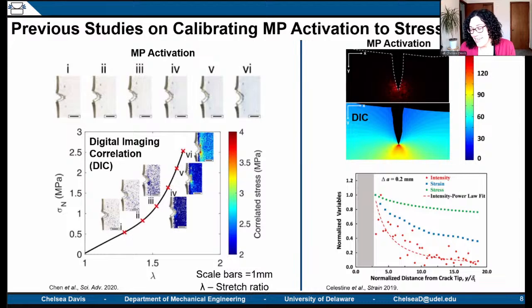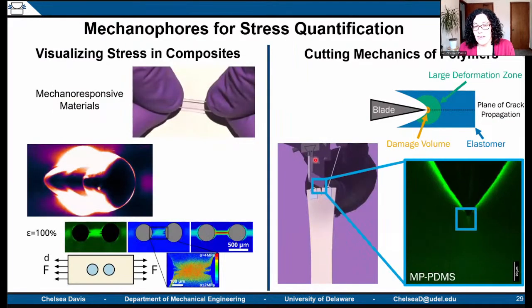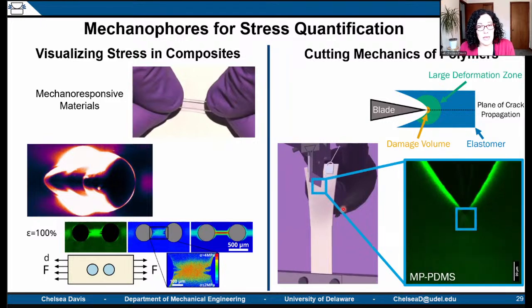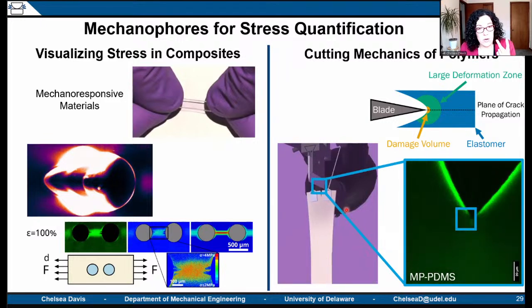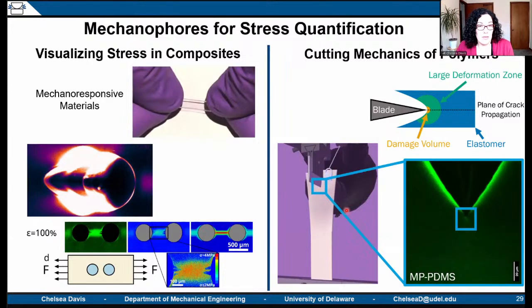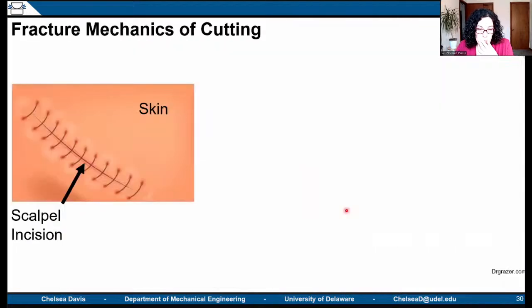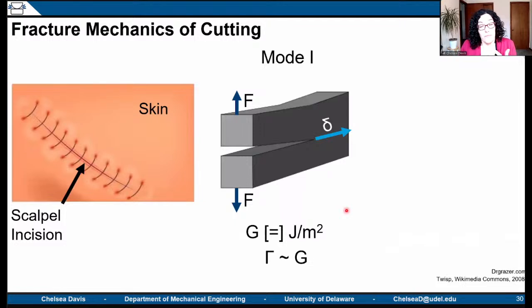So the solution to this is to start thinking about cutting mechanics. In cutting, you control where the fracture is and where it goes by controlling the force that you're applying with your blade. So this should surprise no one, that a sharp blade is better for cutting than a dull blade. You all know this from cutting a tomato or by seeing that surgeons' scalpels are very, very sharp. And all of this relates to the force required to propagate a cut. So what we're interested in is the fracture toughness, or the energy required to create new surface.